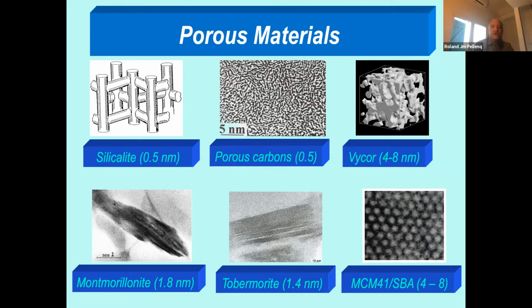Then obviously you have other samples, more ordered, like MCM, SBA - still silica, but made from soft chemistry, where you do this ordering of an organic phase, a surfactant phase, and then you just burn it, and at the end you're left with the porous matrix, and these are proper cylinders. The walls are actually not crystalline, not crystal like zeolite, but the pore size, a few nanometers, is controlled by the size of those organic molecules.